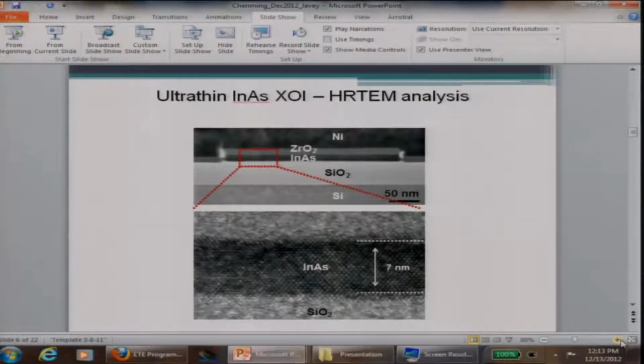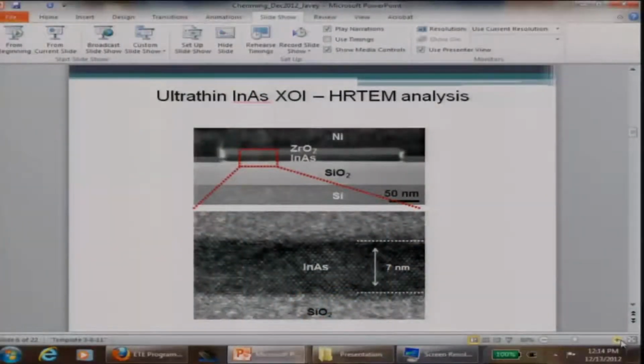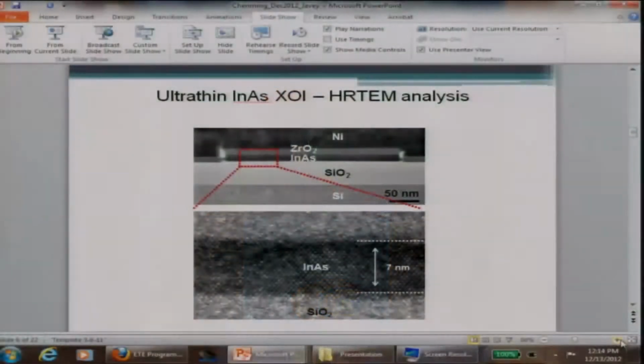So this is a direction that we started roughly 4 years ago at Berkeley. And at the time when we started this, when we showed the results to our III-V colleagues, we only had materials results. There were no device results. The first thing that they said was, well, look at this. You have an amorphous silicon oxide, a single crystalline indium arsenide, and an amorphous layer on top. The interface quality is going to be miserable. That's what they projected. The DIT is going to be miserable. And most likely, you're not going to see any gate dependence, especially for indium arsenide. So the question was, does this structure work? Can we get good transistors out of it? And the short answer is yes.